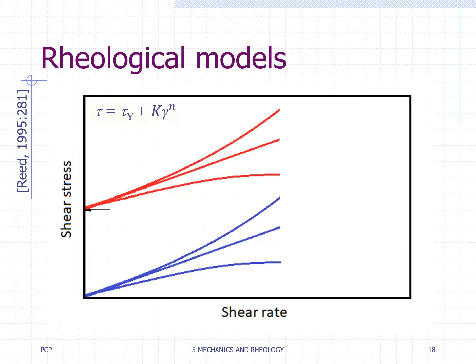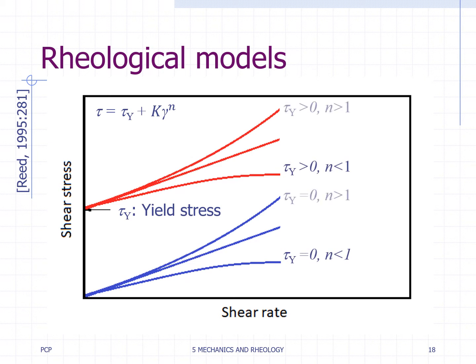A general equation describing those behaviors is the so-called Herschel-Bulkley model, where tau is the shear stress, gamma the shear rate, tau y the yield stress, k the consistency index, and n the flow index. If tau y is larger than tau, the Herschel-Bulkley fluid deforms as a solid, otherwise it flows as a liquid. For n lower than 1, it is shear thinning, whereas for n greater than 1, it is shear thickening. If n equals 1 and tau y equals 0, this model reduces to the Newtonian fluid.